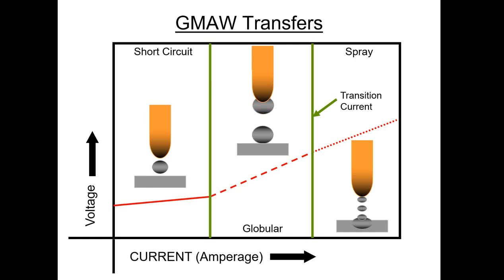The next step is globular transfer. The red line right here represents our voltage. So our voltage is down. Now our voltage is starting to go a little bit higher. Now the wire feed speed is changing a little bit too. But the globular transfer is kind of special, so I want to take a moment on it. Globular transfer represents a danger to welding because you can actually turn the wire feed speed down a little bit and get a weld that looks much better. It doesn't have as much spatter, but it has absolutely zero penetration.